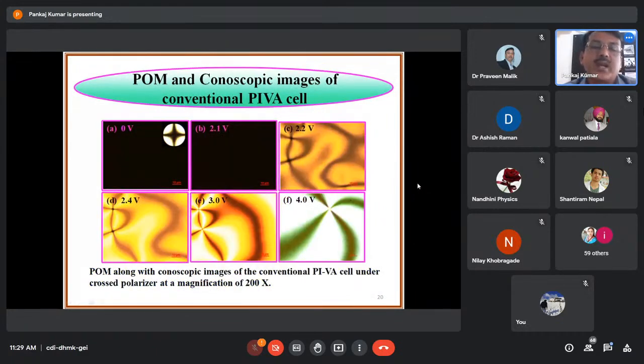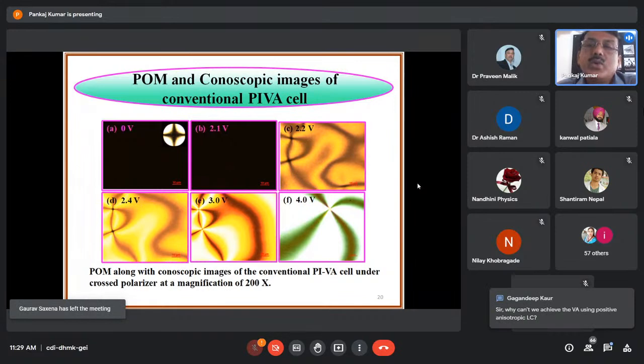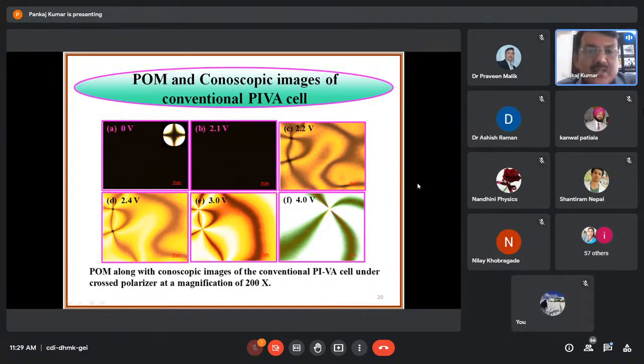But here at 2.4 volt, 3.0 volt, 4.0 volt, you can see these figures, this texture shows that the liquid crystal molecules are not perfectly aligned unidirectionally. It means that they have some drawbacks inside the cells, and that's why we can see these kinds of textures. Under the applied voltage, we want a perfectly bright state for a perfect display device.